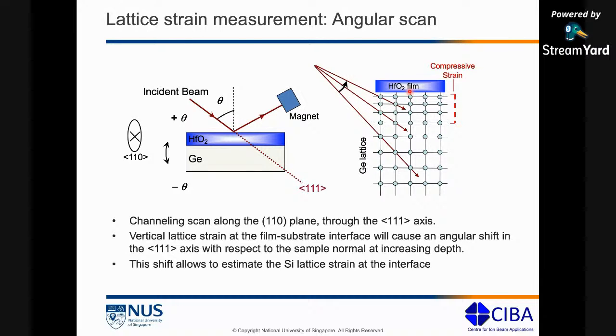So that lattice mismatch is going to give you some amount of strain in your single crystal lattice. As you can see here, this lattice close to the interface is strained, whereas in the bulk it is a perfectly single crystal, right? And this strain can be either tensile or compressive, depending on what kind of mismatch you have. From an electronic property point of view, this strain actually can be useful. Of course, if you have too much strain, that is not good. But some amount of strain is useful in enhancing the electronic properties.